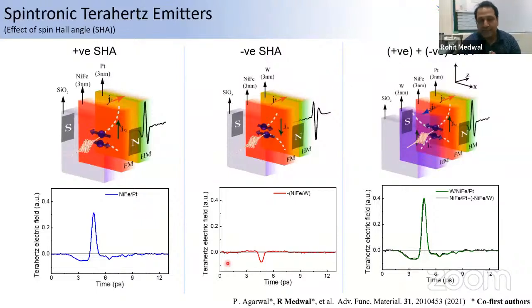So we can clearly show that the superdiffusive spin transport phenomena, where we are talking about the spins being pumped from the ferromagnet to a heavy metal, really dominate the emission of the terahertz photon, not only the demagnetization. So that is the takeaway message from this slide: by changing the spin Hall angle of the heavy metal, which is tungsten and platinum, we can really change the phase of the terahertz photon. That is the first thing.